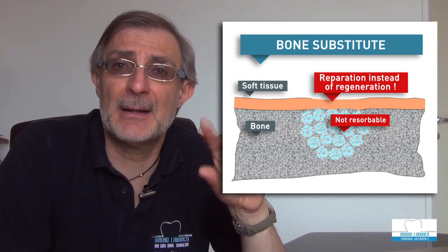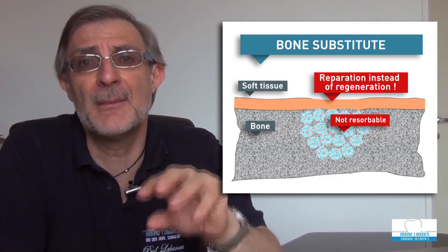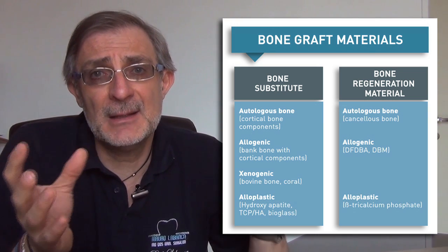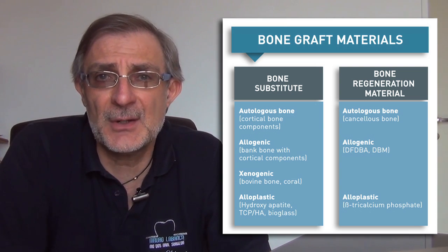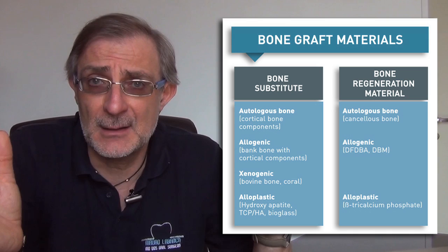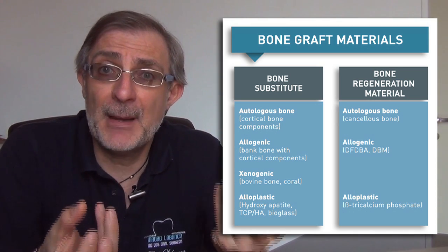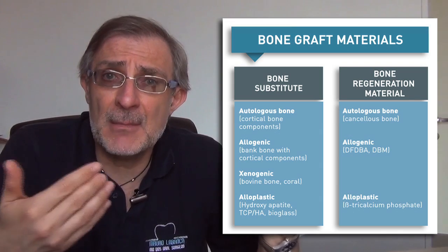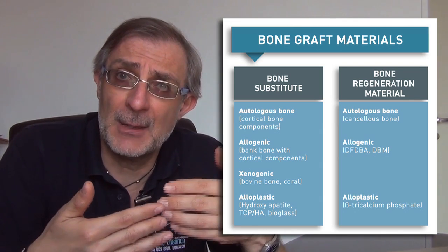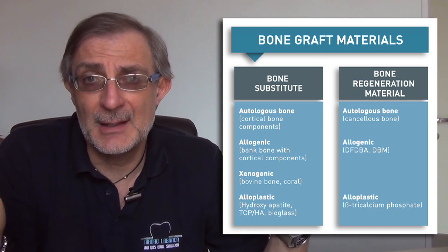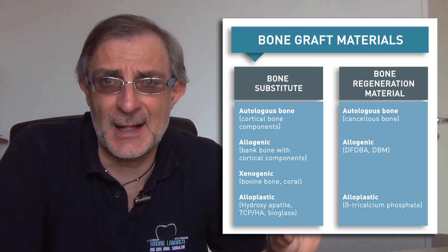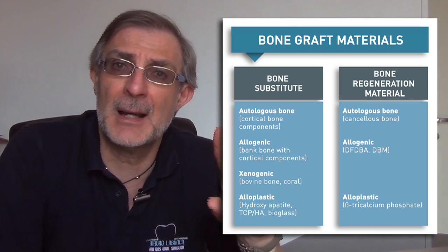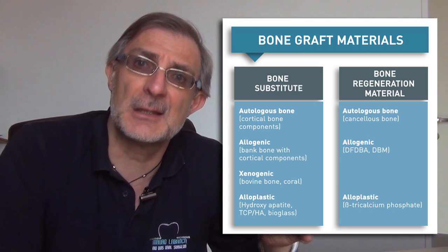Because some particles, some components of the biomaterial will remain there. As we can see in this picture, some materials like the autogenous bone that is usually considered as a gold standard can belong to both sides, depending on the selected properties of the material — if cortical or particulate. In the same concept, all the other biomaterials can be divided between the two lists. The only one that belongs exclusively to one side is the xenogenic biomaterial which, being non-resorbable by definition, will always remain in the category of bone substitute.